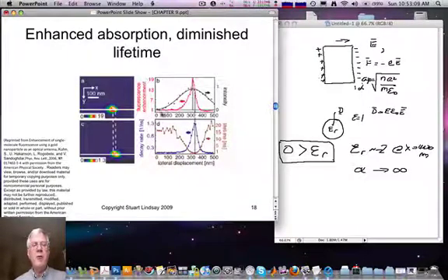Here is a plot of what happens as the laser spot is swept across the surface past a dye molecule. So in the absence of the metal particle is this black line here, and so you see the fluorescence intensity increasing as the laser spot passes over the dye. When the metal particle is placed over the dye, you see that the response is much sharper. Of course, it's not overall higher, presumably because of quenching, but in this region here, where the peak goes over that produced in the absence of a gold particle, there does appear to be significant fluorescence enhancement from the particle.